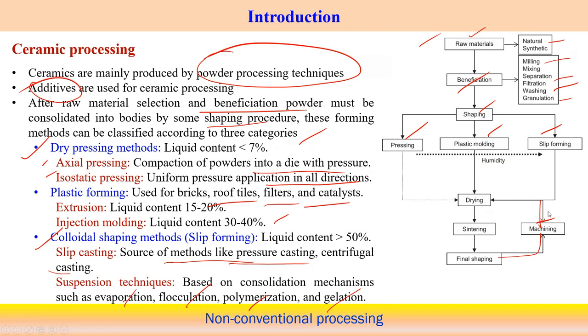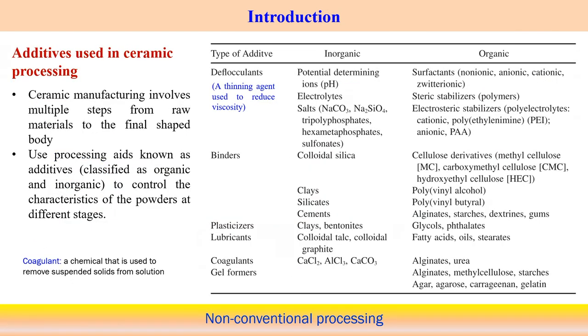One important feature of ceramic processing is the use of additives. Since ceramic processing involves multiple steps from raw material to final shape, processing aids known as additives — either organic or inorganic — facilitate the different steps. Additives are used to control and modify the powder characteristics at different stages of processing. One type of additive is deflocculants, which are thinning agents used to reduce viscosity. Inorganic deflocculants include potential-determining ions, electrolytes, and salts.